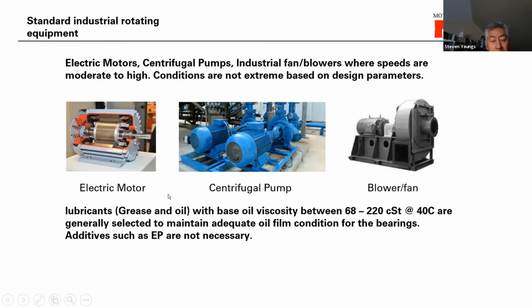And for these equipment, normally if I have to select a grease or oil for it, a base oil viscosity between 68 to 220 at 40 degrees C are generally very good enough to get that oil film established for the bearings. And because of that, normally EP additives like anti-wear and EP are not really needed because the oil film is there to separate the rolling surfaces. All right.